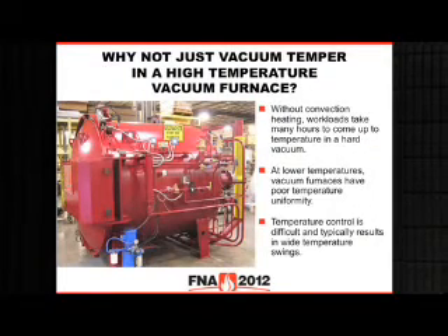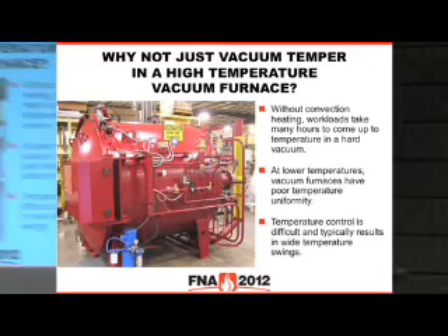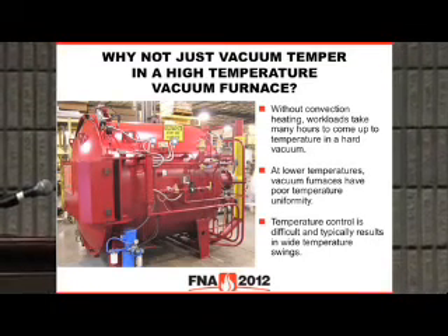We get this question a lot, and this is actually a viable way of vacuum tempering: if you have a high temperature vacuum furnace, just temper in there. But what you'll find is that a lot of the tempering of tool steels is done at 1,000 degrees, and you'll find that a traditional hard vacuum furnace at 1,000 degrees takes a long time to heat a load. We've actually seen it take as much as 12 hours on a dense 36 by 48 by 36 load with multiple layers and multiple rows.